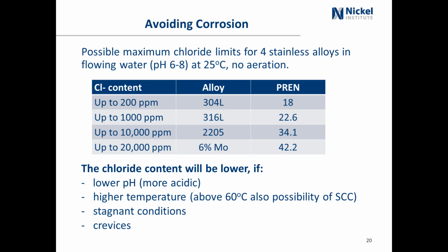But if you lower the pH and you make the solution more acidic, the chloride content that the stainless steel is going to be able to resist is going to be lower. And if you increase the temperature, the amount of chloride that the stainless steel can resist is going to be lower. And if it's stagnant conditions, again, the chloride content level would be lower. And if there's crevices, the chloride content would be lower. So it's not just simply to say, oh, what chloride level will a stainless steel resist? There are many, many factors that affect that.